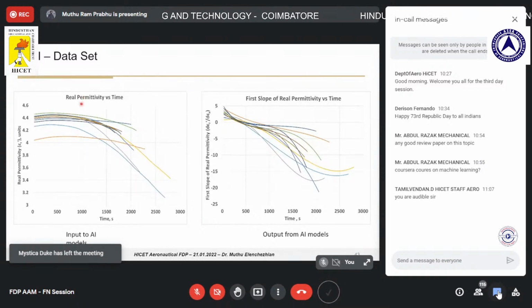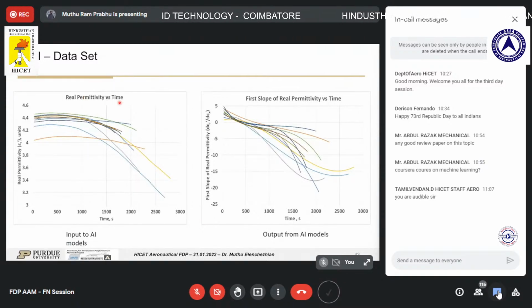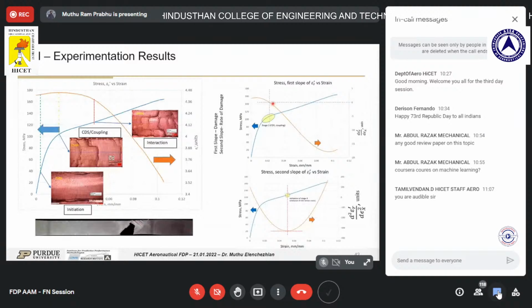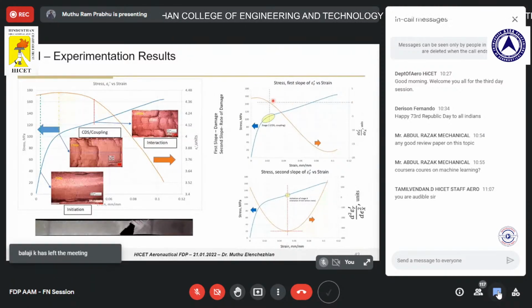We collected the actual dielectric value versus time, and obtained the first slope of the values versus time for this curve. And we wanted to predict, given the real permittivity values, the first slope value. Because the point at which the first slope value crosses 0, that is, where it changes from positive to negative, is identified as the characteristic damage state point, where the actual stage 1 changes to stage 2.